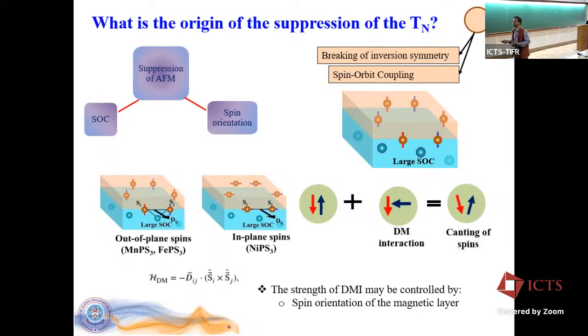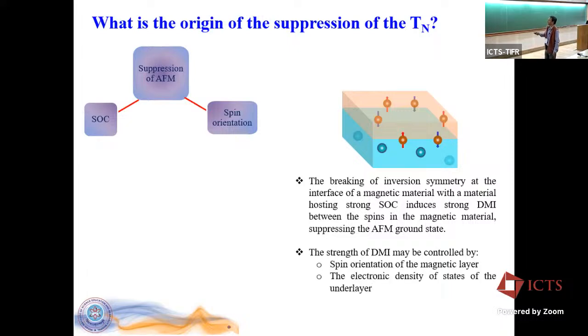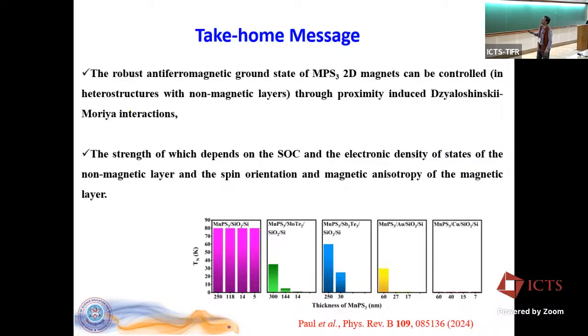At the same time, since we could see that different substrates having different charge density of states also play a role in the degree of suppression of the Néel temperature, we believe the charge density of states is an important player apart from the SOC and the spin orientations. So these are the two important factors that we learned. The spin orientation is an important player and the electronic density of states is another important player in deciding whether or not the spin interactions could be tailored. This is the take-home message from this experiment: the SOC is an important player, and the electronic density of states is also decisive.